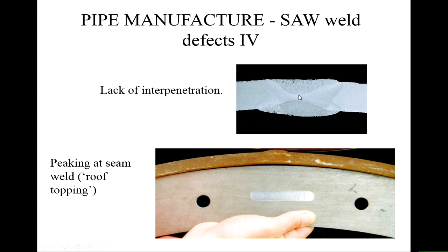And the other one here, this is the one that's impossible to see from most analysis unless you use your automated ultrasonic systems. You've got here the joint between the two pipes with no weld metal in it at all. So this is one submerged arc weld, this is the other one, and there's a bit in the middle that's not welded. And so that can be quite a serious failure.